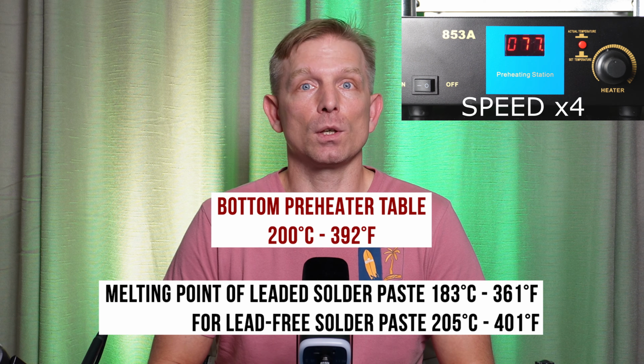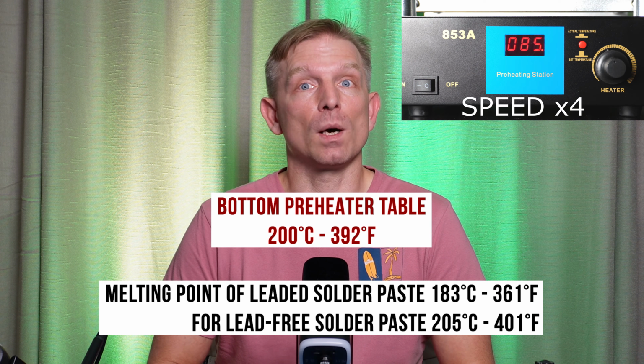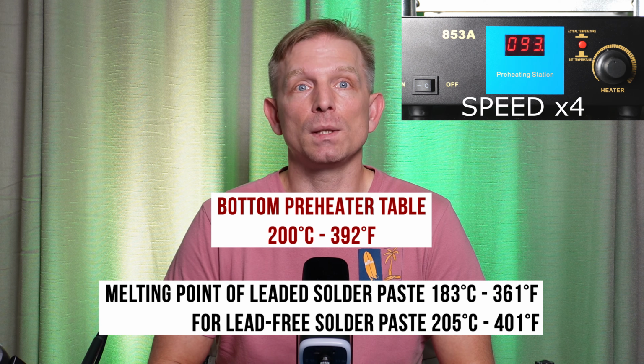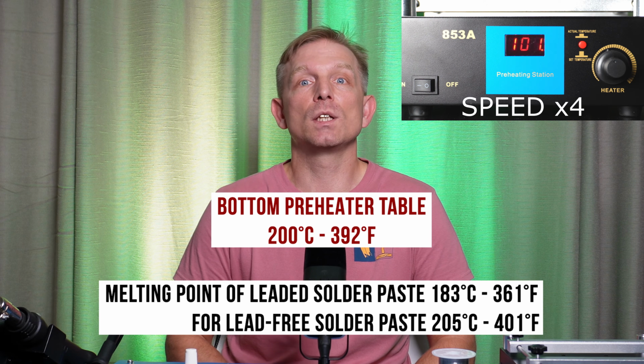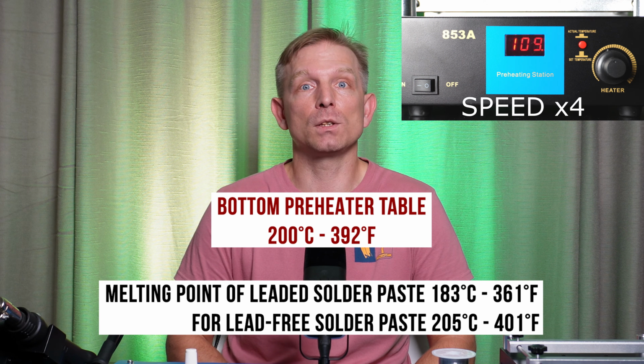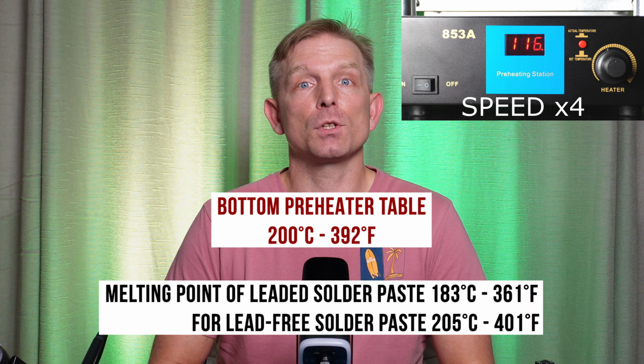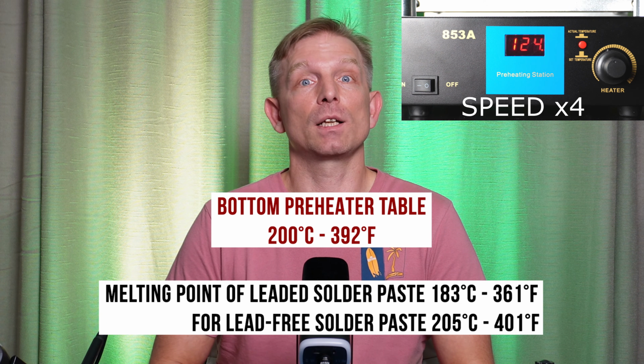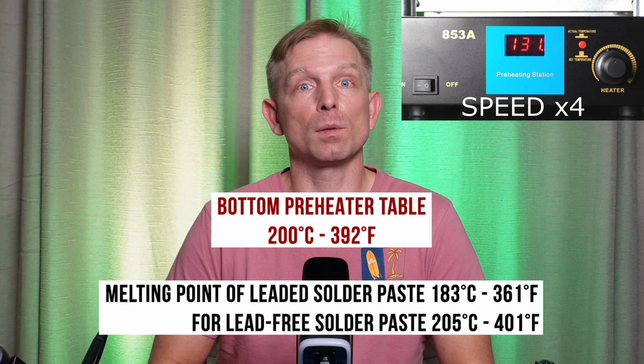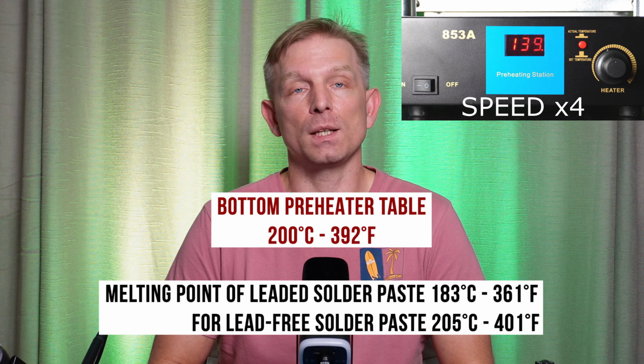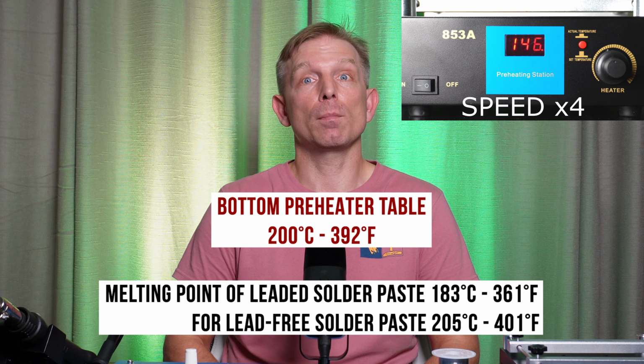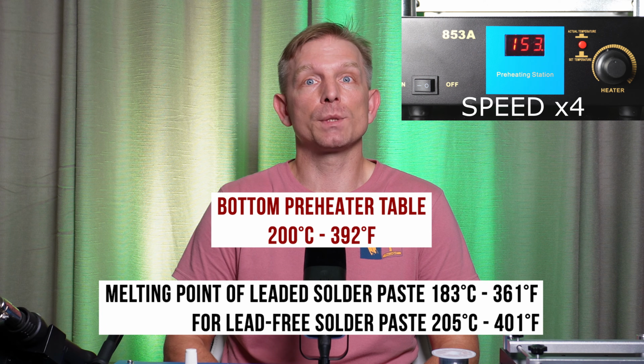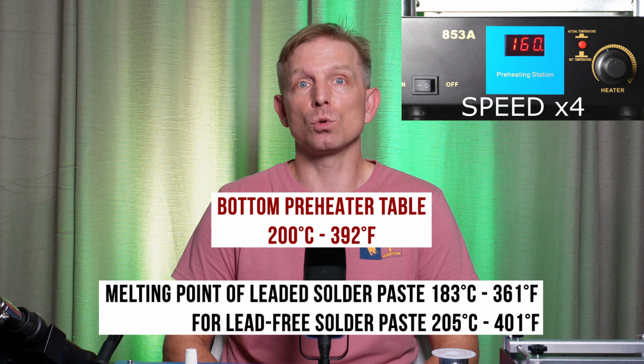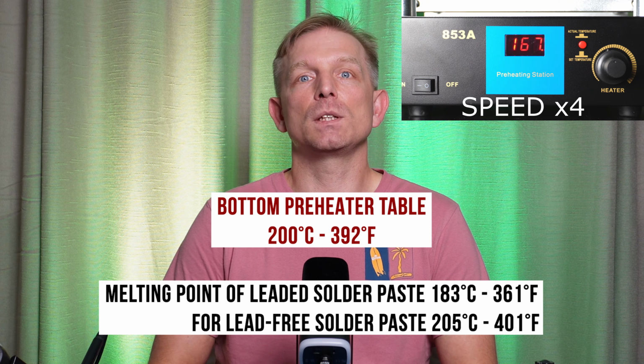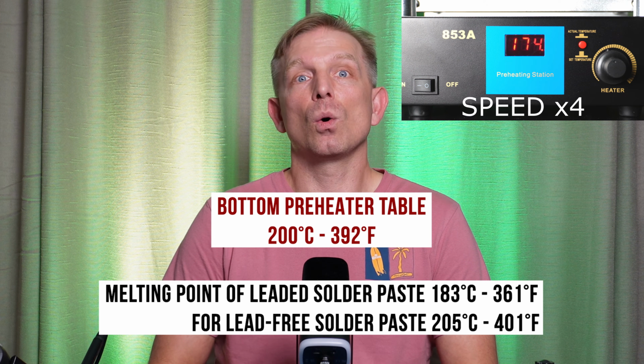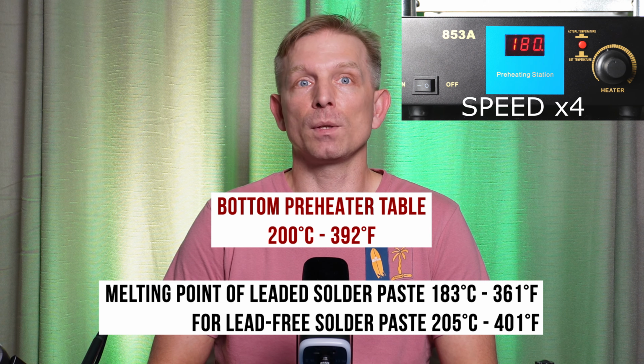Don't place the PCB early because the preheating surface warms up slowly and you can damage the PCB laminate. Long exposure to heat may cause delamination of the FR-4 PCB material due to overheating. In a professional reflow oven, the PCB heats up and reflows according to the defined thermal profile in about 4-5 minutes. A bottom preheating table warms up much slower and can cause the PCB substrate to blister or warp if exposed too long. In my case, I will place the PCB on the hot surface or holders only for a short time and nothing will happen to it.